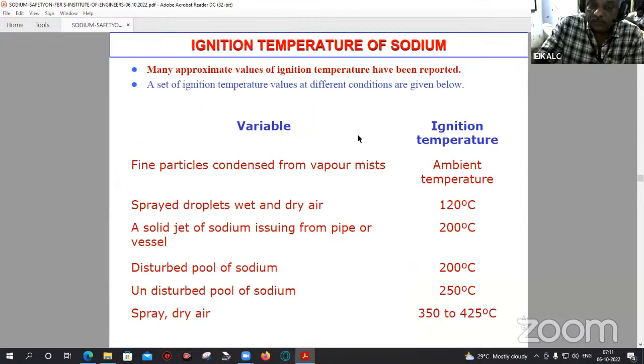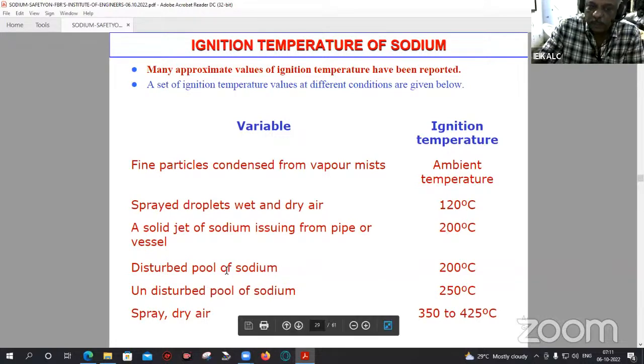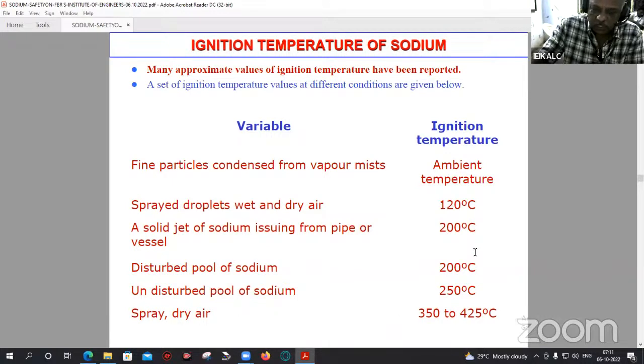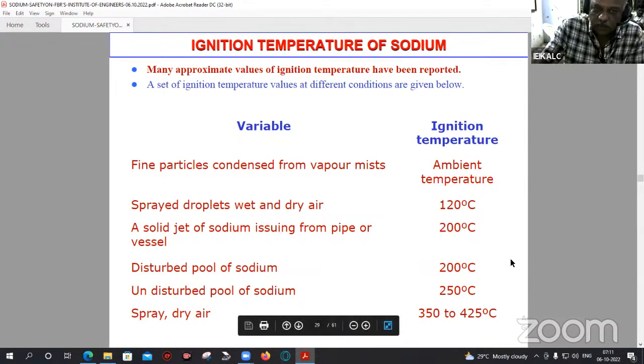And these are some experimental numbers with respect to the ignition temperature of sodium. Fine particles of condensed sodium, like vapor mists, can ignite even at ambient temperature, depending upon the surface area. Sprayed droplets, in wet and dry air, ignite at 120 degrees centigrade. A solid jet of sodium issuing from a pipe or vessel at 200 can also catch fire. A disturbed pool of sodium at 200: you cannot rub it. Suppose sodium is hot, you just give some friction, it can catch fire. Or using a stirrer, if you stir it, it can catch fire. Okay, and this is about the ignition temperature.